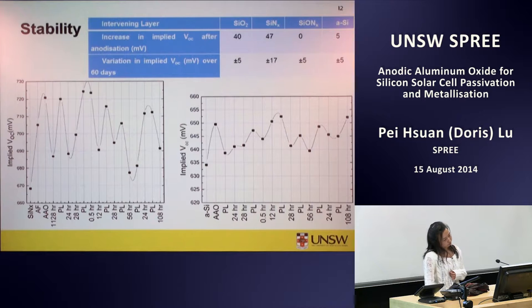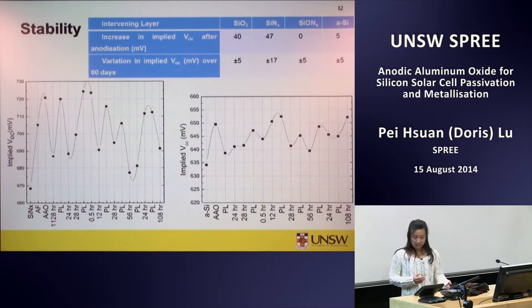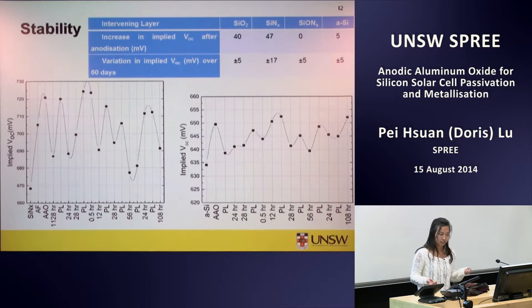However, it varies over around 60 days, in a range of nearly 20 millivolt, and every time after PL imaging, the lifetime jumps back. So we suggest this variation might be recovered by light, which is sensitive to the light.